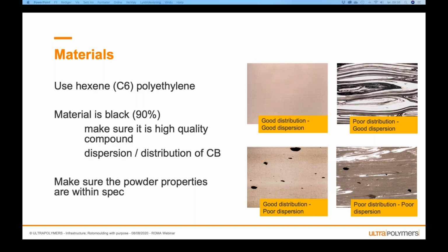I agree that on all other tests, you can do compression molding specimens. But for impact, you should use arm impact on a rotomolded sample. Then you know that you're testing it on a proper sample. That is what they do in the rotomolding world. And if you have homogeneity problems, you will see it immediately.